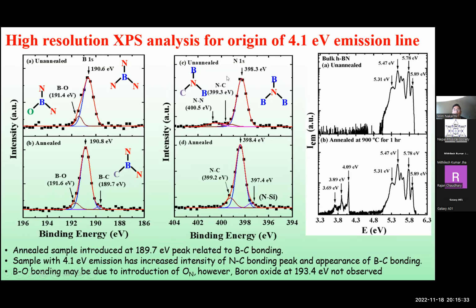And in the nitrogen binding energy case, it has the binding with nitrogen and carbon. This peak indicates that it is enhanced. So that means in the sample which has 4.1 eV, there is some carbon bonding with boron, and there is more carbon bonding with nitrogen. So it indicates carbon is playing some role in generating the 4.1 eV.